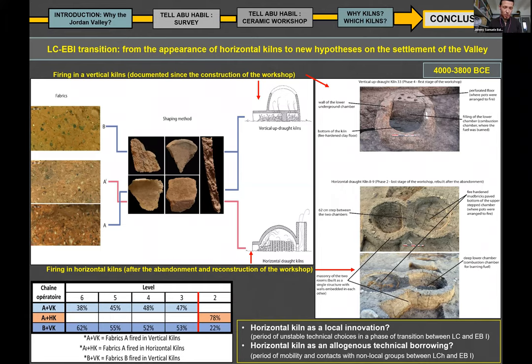there are two distinct groups of craftspeople, most probably belonging to the same lineage in the broad sense of the term, because they made ceramics by the same modalities, in this case by the same operational sequence documented throughout the Southern Levant during the Chalcolithic, and so far everything is good, everything is normal. But kilns are problematic. Since the first construction of the large workshop identified at Tell Abu Habil, craftspeople who shaped A and B paste according to the single shaping method fired both in vertical kilns, always vertical kilns, which are also documented in the rest of the Levant at that time. They are not very well documented, but we have some parallels.